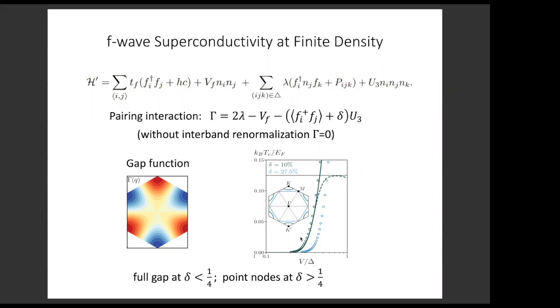Also, there was an early question about doping dependence. When the doping is small, less than 1/4, the Fermi surface is around the K and K prime points, and in that case the F-wave pairing leads to a fully gapped state. As the doping increases above 1/4, the Fermi surface becomes a singly connected pocket around the gamma point, and then the F-wave order parameter has nodes along the gamma-M direction, so it will lead to a nodal F-wave state. One can imagine that right at 1/4 filling, or in the vicinity of it, the Van Hove singularity may lead to competing states between density waves and superconductivity, etc.